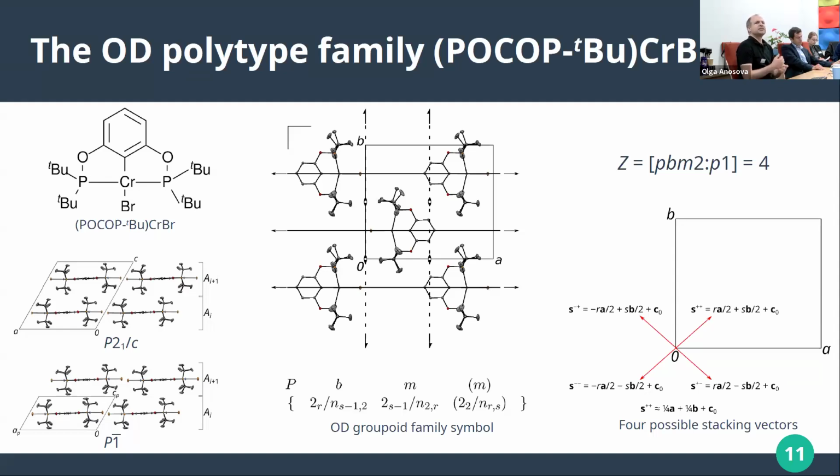And it's quite obvious if you look already at these two different polytypes. They have different stacking. So you see they have this layer in common. And again, here we look, C is now going down. And this is one of the layers. You identify the symmetry of these layers. It's not perfectly realized, you see it here, but it was PBMM. So the reflection plane in the layer, then the reflection went horizontally and the glide plane vertically.